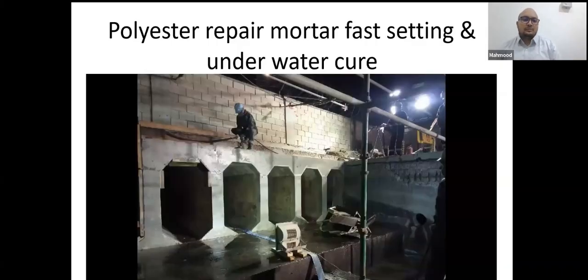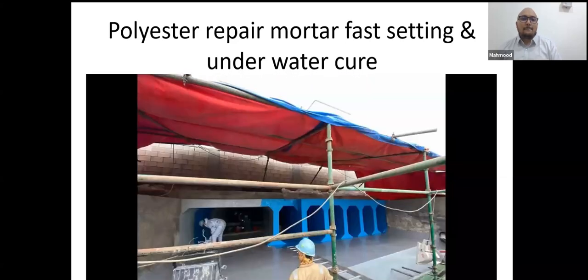This is the after repair. Initially, we saw the photo, how it was damaged. It is 100 Newton per millimeter square after curing, which is 3 times the strength of normal concrete. Normal concrete is just 30 Newton, but this is 100 Newton per millimeter square. It's been coated with the polyurethane coating, blue color.